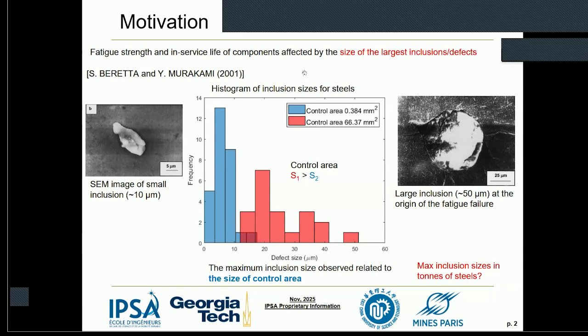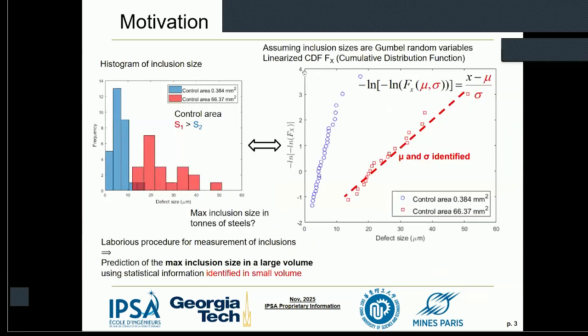So the question is raised: when we observe tons of steel, we can always expect a larger inclusion. So how can we estimate the largest inclusion size? In order to address this kind of problem, typically we can use a statistical way, such as this one. On the right-hand side is the typical histogram of the inclusions, and we can also use the CDF, which is used to collect the statistical information.